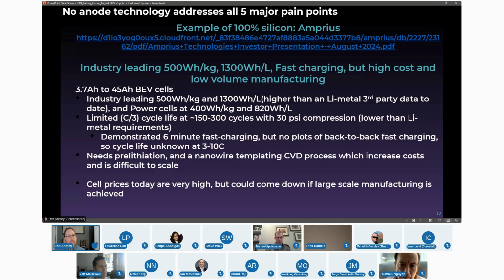But in some cases, you really need less than 10 PSI, so that will limit applications because all these are pouch cells. They're not prismatic cells. They don't come with their own compression. And their CVD process to form the nanowires does limit the volume they can make and the cost they can make it at. Now, to be fair, they are launching a new product line, which is a silicon carbon composite, actually. And that is going to dramatically lower the price and increase the volumes they can manufacture. And we're still waiting to see third-party data from that, but that's really exciting.